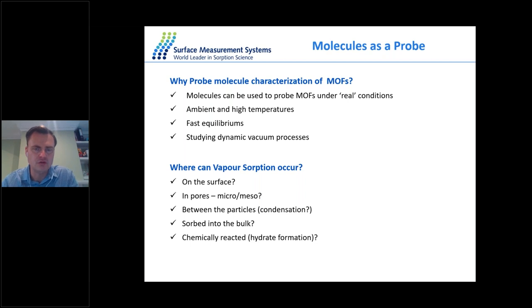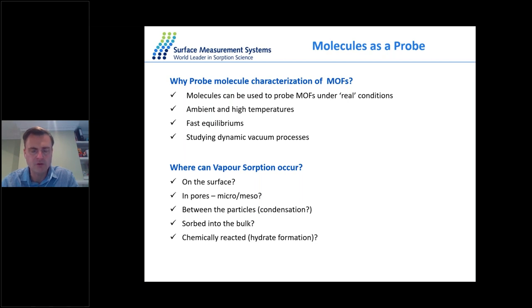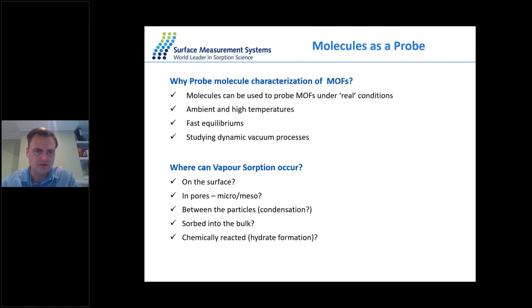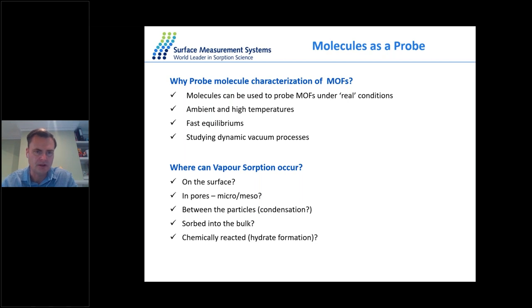You may wonder why we use probe molecules to characterize metal organic frameworks. One of the main benefits is that we can study MOFs under real conditions. When MOFs were first introduced there were very promising applications, but when industry started using them they found that most MOFs are not stable under real conditions — meaning ambient temperatures rather than under vacuum. Adsorption measurements let us look at the stability of MOFs in the presence of humidity, which is very critical, and also when exposed to CO2.